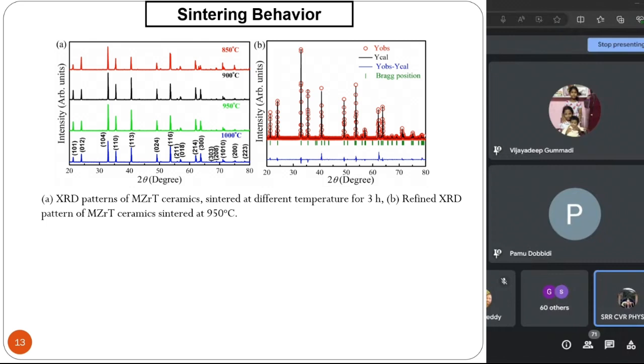So that's what I have shown you in the literature review, that these people have sintered at 1400 degrees and all. Now, since we have started with smaller particles, as I showed you in the previous slides, about 30 to 40 nanometers, we started sintering at 1000 degrees C, 950 degrees C, 900 degrees C, 850 degrees C, to see whether the density of the material is coming or not.